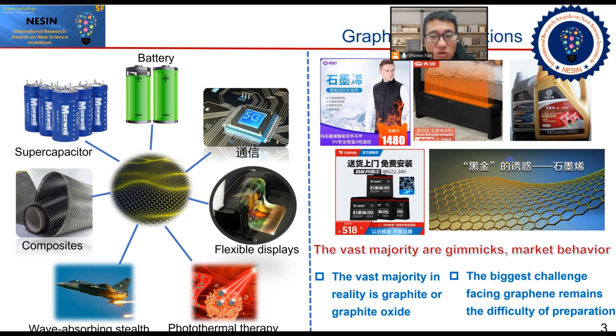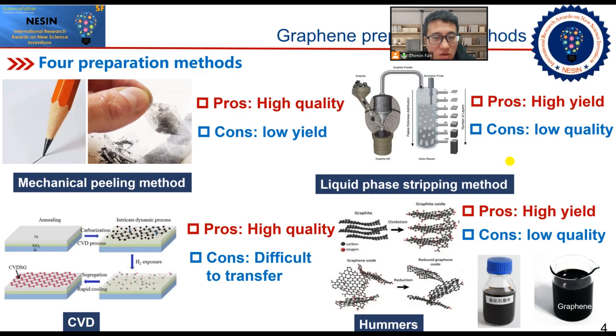Then why is graphene so good in nature and so much worse in performance in practice? In fact, the vast majority of graphene in the market is not really graphene, and the biggest challenge facing graphene remains the difficulty of preparation. There are four main methods of graphene preparation: mechanical exfoliation, which involves peeling graphite with tape, and liquid phase exfoliation, which involves exfoliating graphite in organic solvents using ultrasound. The disadvantages of these two methods are obvious: one is extremely low yield and the other is poor quality. The fourth method is difficult to transfer and extremely expensive.